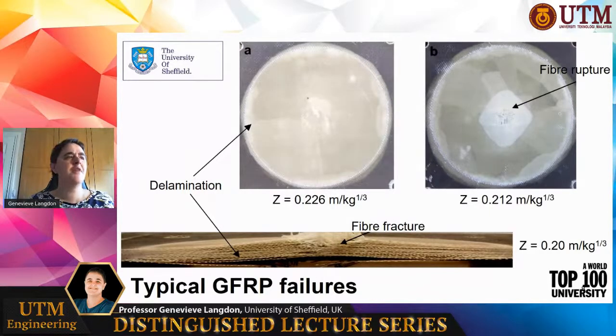So it's a scaled type of distance. So if you have a Z number that's less than one, you've got explosive that's extremely close to the panel, and we call that near field loading. If Z is greater than one, then we have something called far field loading. And that is usually more uniform and has lower pressures than these localized blasts. So most of my work is focused on the more localized extreme types of loading that you see from near field, which is a more worst case condition for a fiber reinforced polymer that tends to be weak in shear